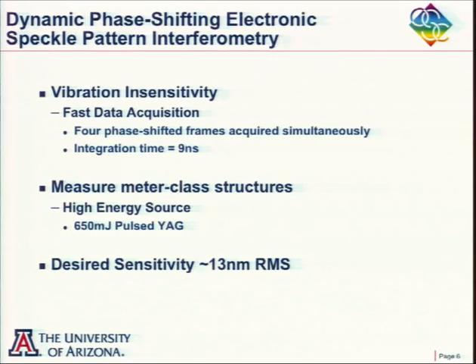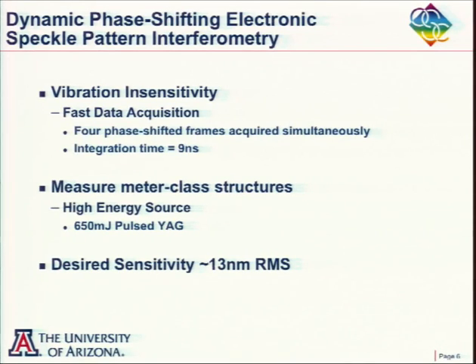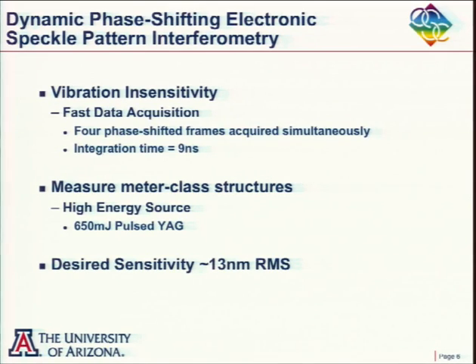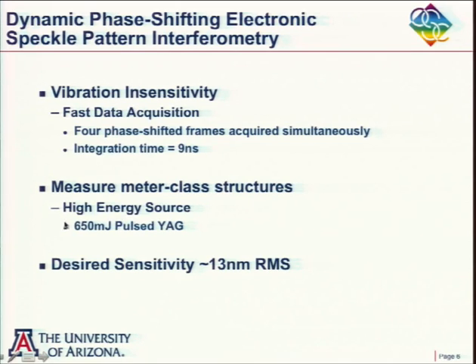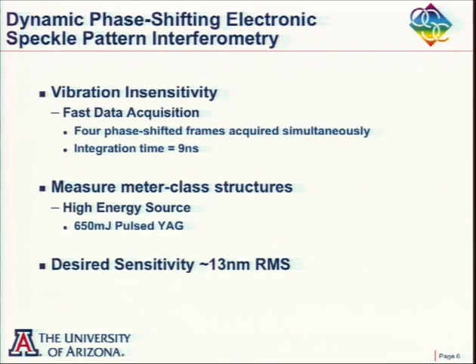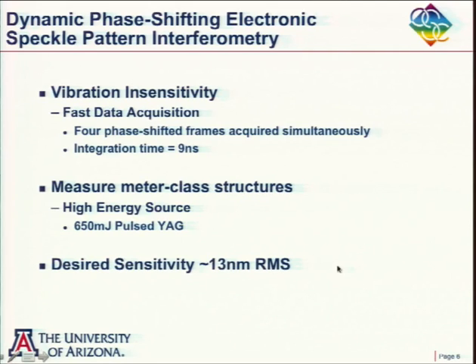The structure holding the mirrors for the James Webb Space Telescope is going to experience mechanical loads and temperature variations. The question is how this back frame is going to deform. The back frame is carbon fiber — a diffuse surface that doesn't scatter very much light. In order to do the measurements, we needed a pulse laser, and we can do our four phase-shifted frames in something like 9 nanoseconds, with sensitivity down to about 13 nanometers RMS on the change in the shape of the surface.